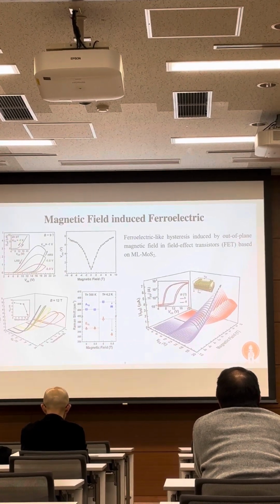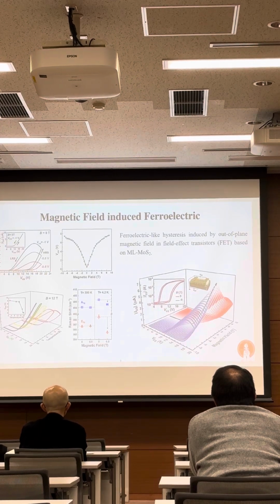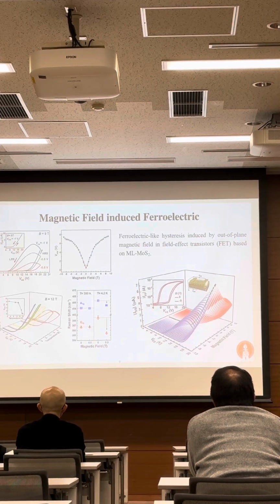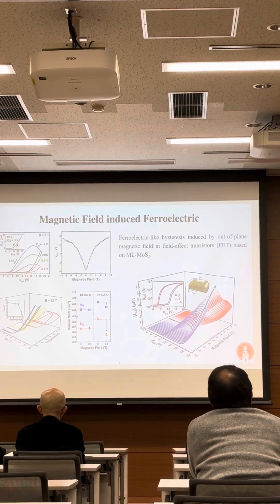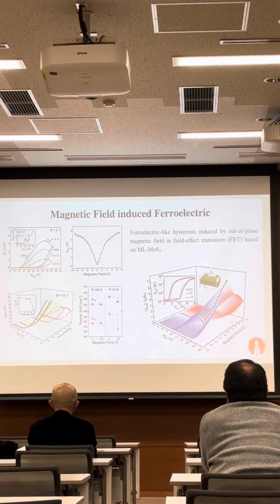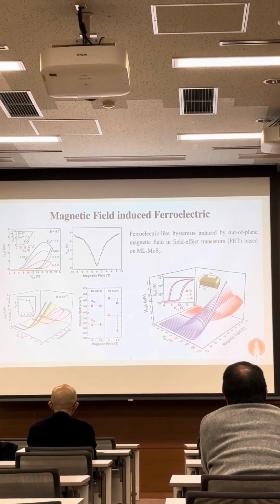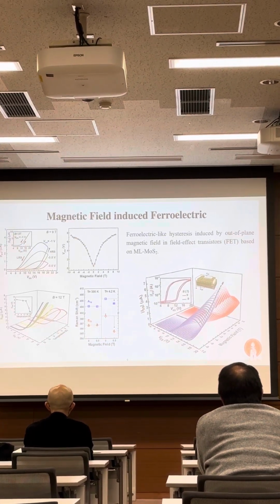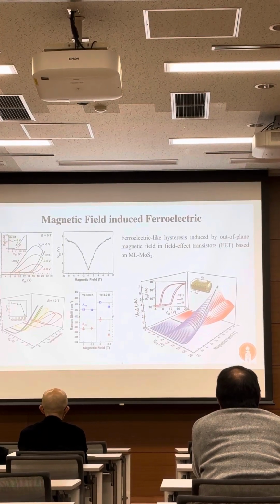But if we apply an out-of-plane magnetic field, we could see that a significant redshift is found at about 4.2 kelvins. These findings strongly suggest that under a magnetic field below certain temperatures, the MoS2 lattice will experience a tensile strain that gives rise to small lattice expansions, instead of the phase transition that we thought before.